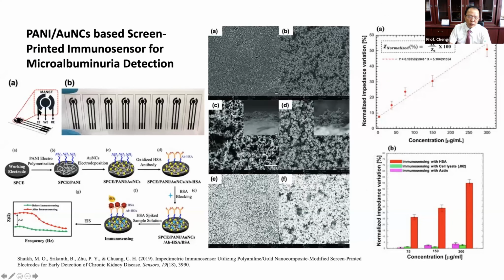For this other sensor, we still use the screen printing carbon electrode, but this time we don't use any particle. We first deposit the conductive polymer polyaniline onto the carbon electrode, so we can have the amino group on the surface. Then to increase the sensitivity, we do electrode deposition with gold nanocrystal onto the polyaniline surface microstructure. You can see this is the polyaniline microstructure. It looks like a tree. This tree structure is a porous, 3D structure that will make this sensor more sensitive.